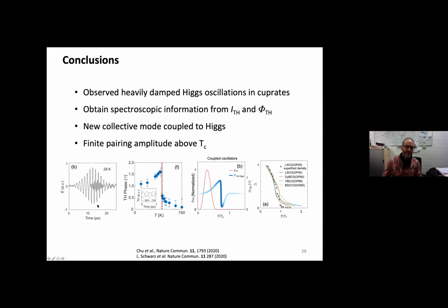I've shown you that with these high field nonlinear terahertz drives, it is possible to excite and drive Higgs modes now also in cuprate superconductors, seen here by characteristic third harmonic generation. And by looking not only at the amplitude response, but also at the phase response, we can see how this mode is coupling 2 different modes in the system. The big question is still, what is the nature of this mode? And the last thing is that this method gives us a new powerful tool to evaluate finite pairing amplitudes in superconductors that are happening even above TC.